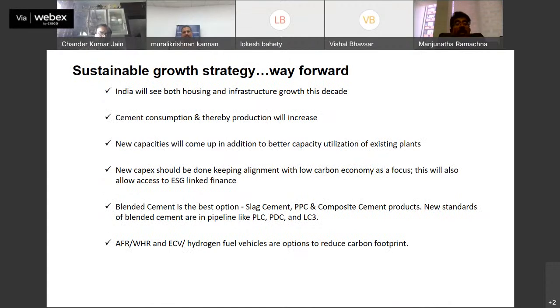The way forward in India, as we continuously grow in terms of housing, infrastructure growth, expressways, and corridors, is that we continuously use cement. So we should go with blended cements. When you have an RMC batching plant, go with a blend of GGBS or fly ash or ultrafine materials to reduce the clinker factor. This is what we would like to advocate.